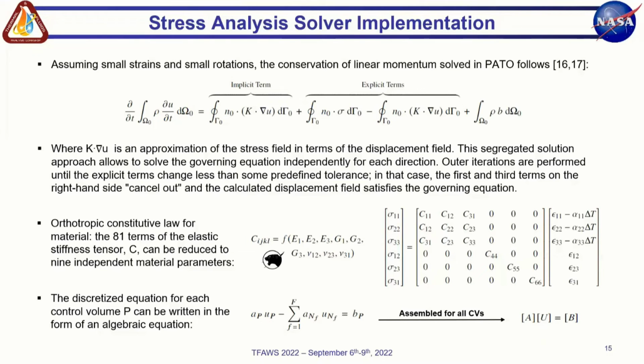And at this point, the implicit term and the second explicit term cancel each other, and the calculated displacement field satisfies the Navier equation. This solver works for isotropic and orthotropic material, following the constitutive laws shown here, and for the orthotropic case, it needs 9 independent material parameters, which are the orthotropic mechanical properties, and we can obtain them with PuMA, for example.